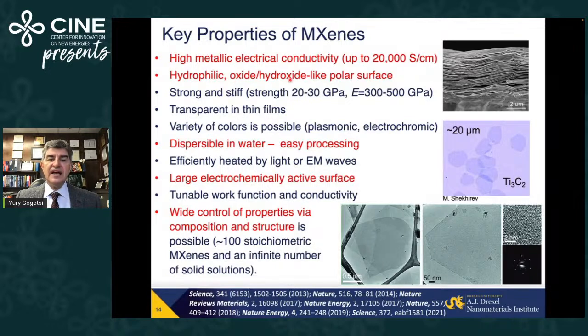They have oxide-like or hydroxide-like polar hydrophilic surfaces. So you can look at them as conducting clay or a water-soluble two-dimensional metal. No other material combines those properties. Again, take graphene as the most common, best known 2D material. Pure graphene is hydrophobic, cannot be dispersed in water, cannot be processed from aqueous solutions. People oxidize it in acid, make graphene oxide, process it, and after that reduce it to benefit from conductivity. MXene has both properties in one material.